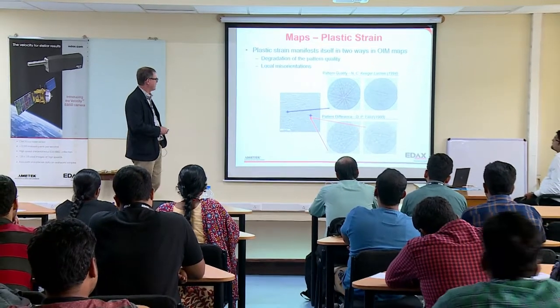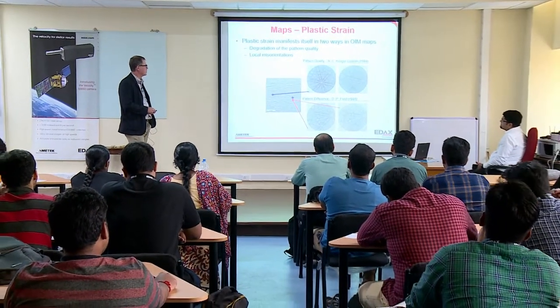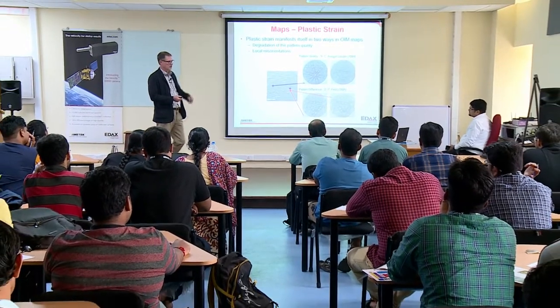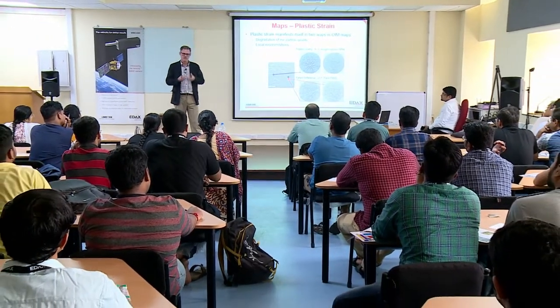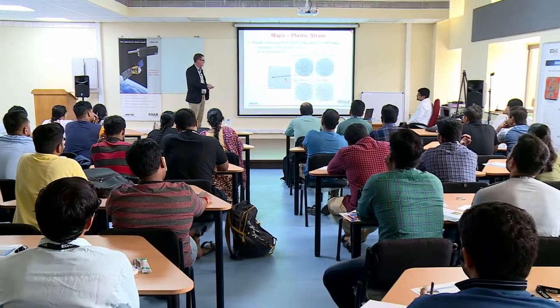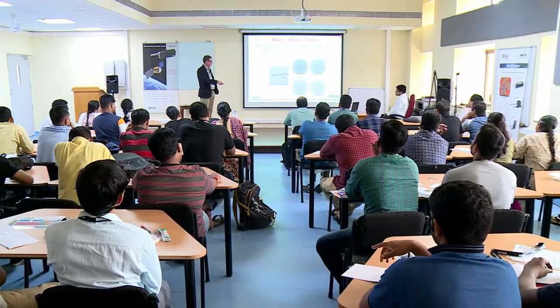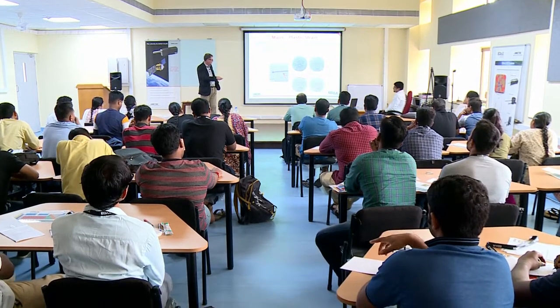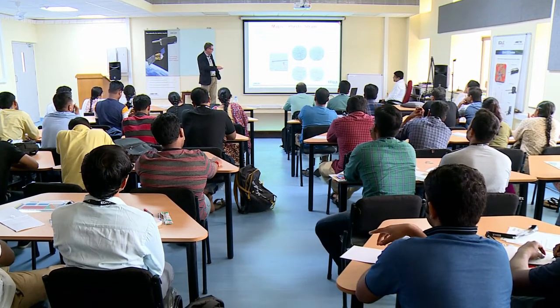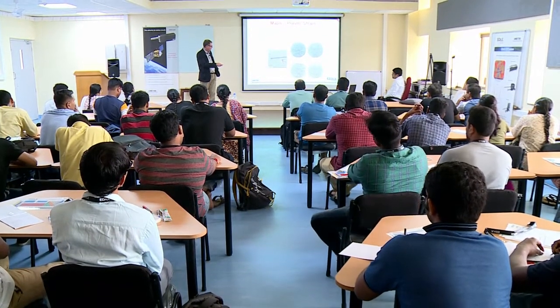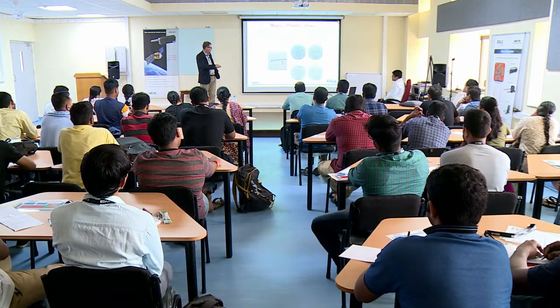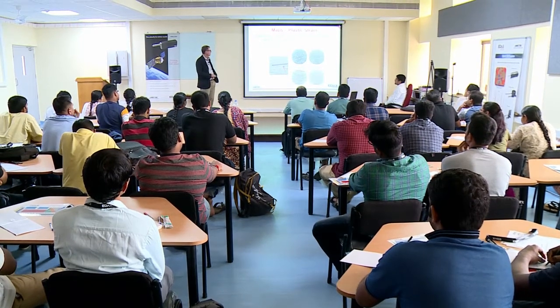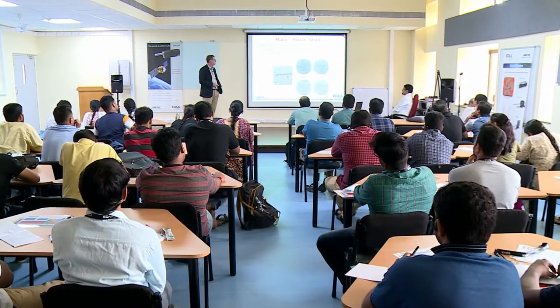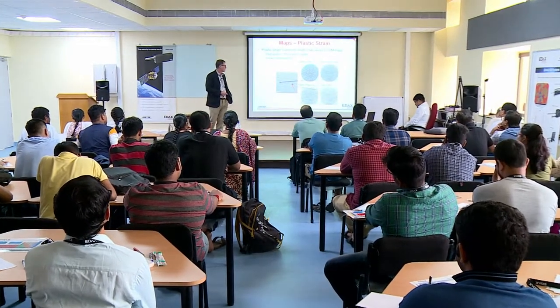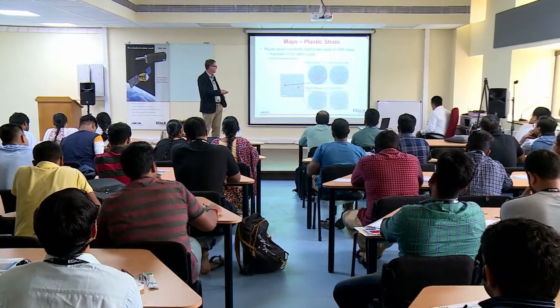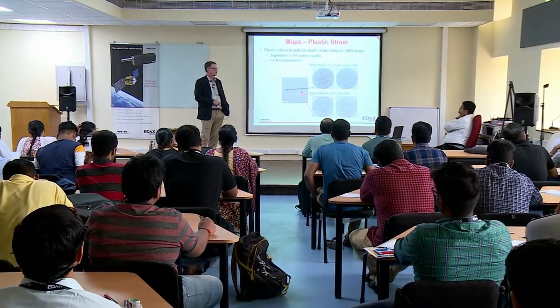The other way that strain manifests itself in the material is a slight change in orientation. As the material deforms, it slips, and you get very small rotations. And so the pattern difference here, you probably can't even see by the naked eye, but if you look really close, this zone axis right here, and that one, it's a little farther away from the edge here. So there's a slight change in orientation across that grain. And we call these local misorientations, and they tell us something about the material. So strain manifests itself in terms of poorer patterns and also changes in orientations.